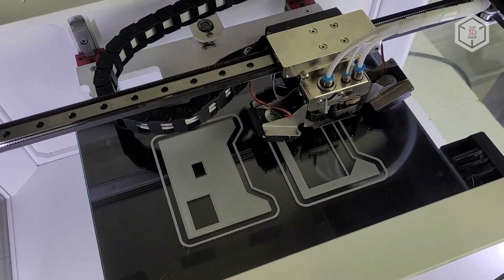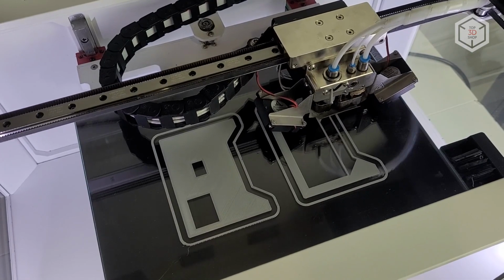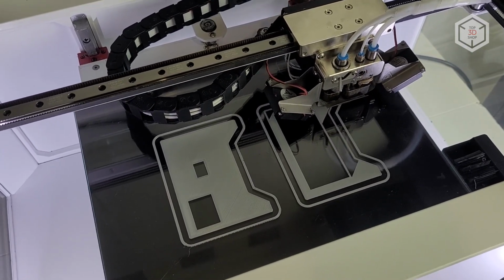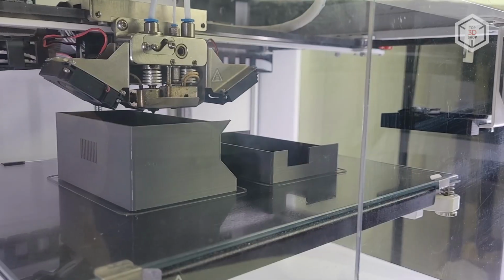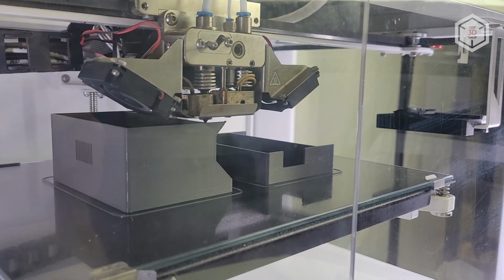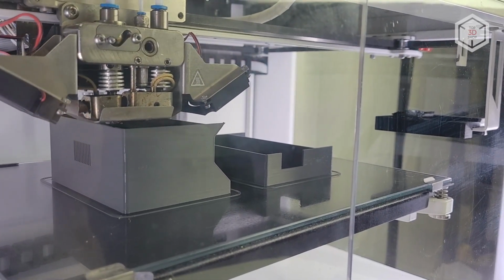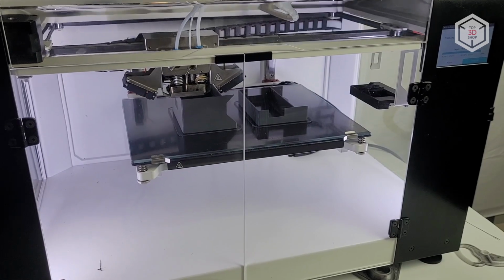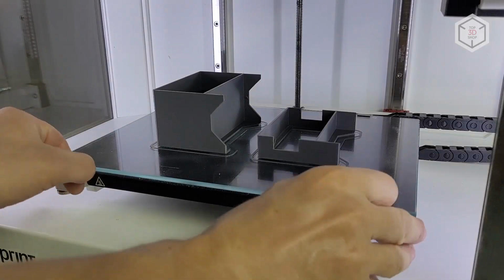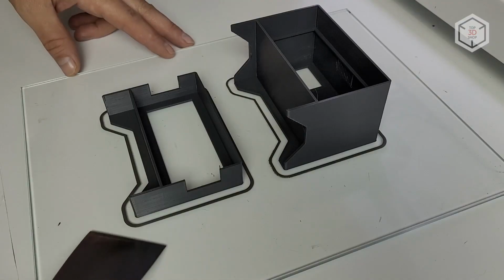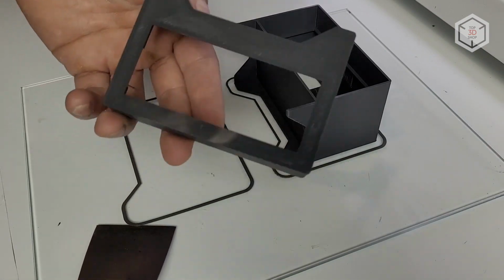For the next test, we decided to check how the printer would manage simple printing with randomly chosen old cheap ABS plastic without any reinforcements. We printed some housing parts for the power supply unit. Everything went well. Thanks to the passively heated build chamber, no shrinkage of the ABS occurred during the process. The corners did not peel off, the thin walls did not crack. After the cooling, the parts remained flat.